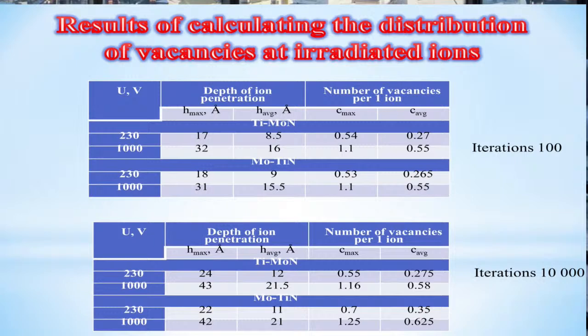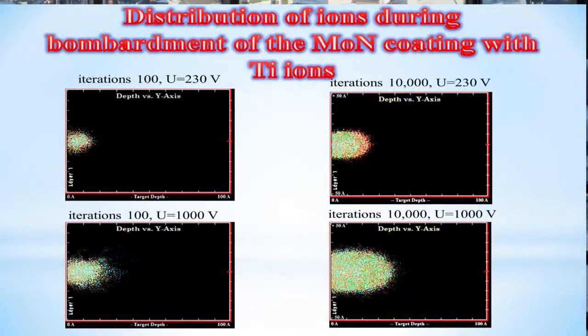It can be described on the basis of the mechanism of formation of the thermal peak. This mechanism is based on the fact that with an increase in energy of implanted ions, the volume occupied by the thermal peak generated by each collision increases. On the next slide, we can see distribution of ions during bombardment of the MoN coatings by titanium ions.